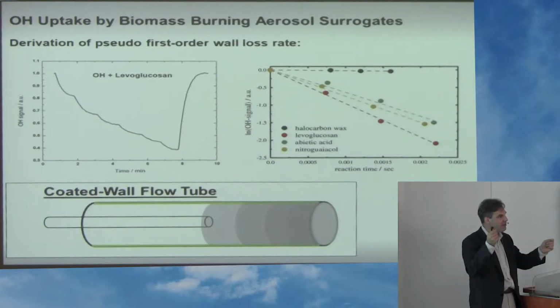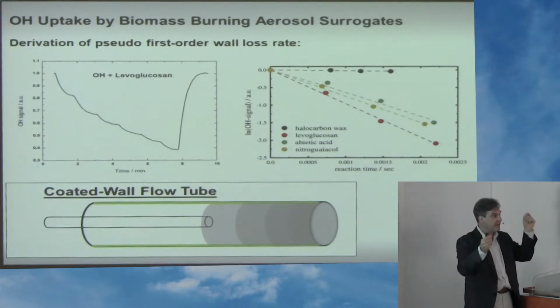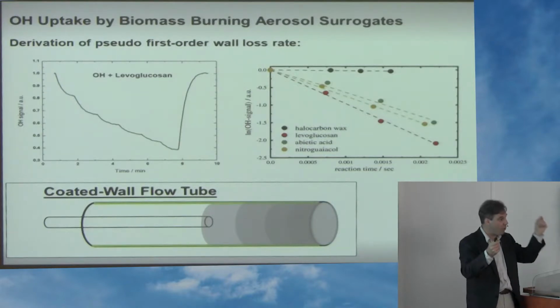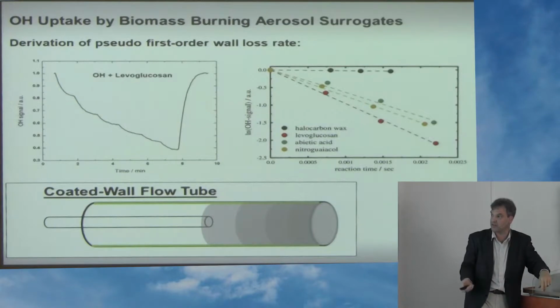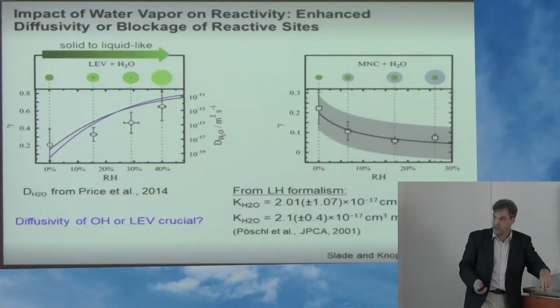From this we can derive a pseudo-first order heterogeneous kinetics. It's not like gas chemistry, OH reacting with methane — it is truly the reaction rate between OH and the substrate, heterogeneous or multiphase kinetics. The steeper the slope, the faster the reaction. So we did this.